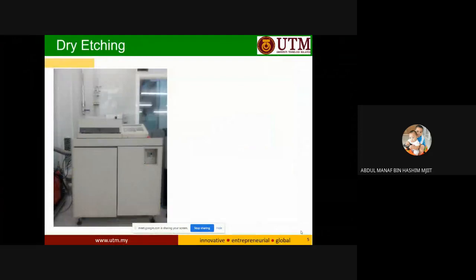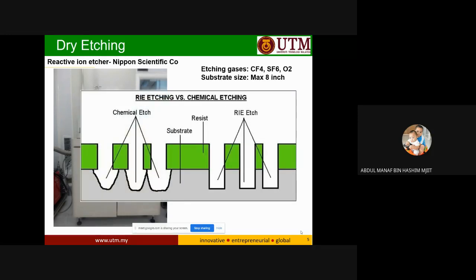Okay, the next is dry etching facilities. We have a reactive ion etcher, RIE. Okay, the gases that we have are CF4, SF6, and also oxygen. And then the maximum size of the substrate that can be put in the system is 8 inches. Just for information to the students, for the RIE etching, depending on the condition of the etching, you can get a very nice, sharp pattern, I mean structure, compared to wet etching.